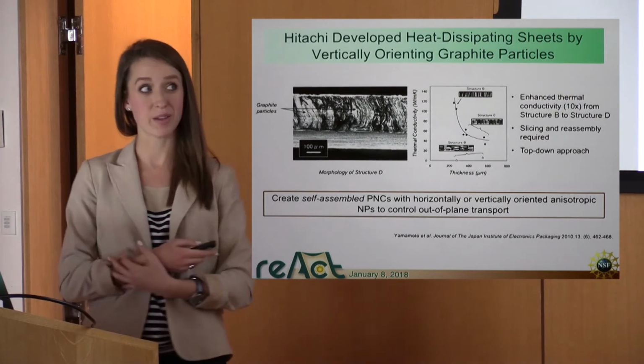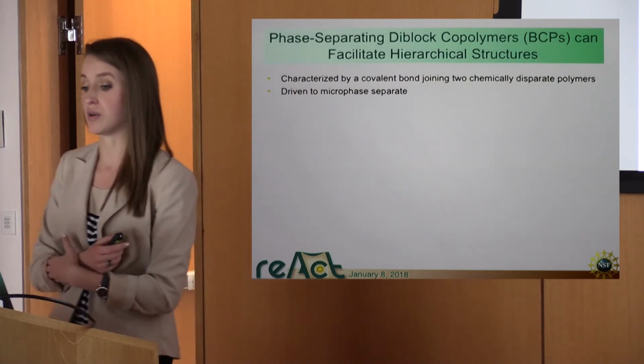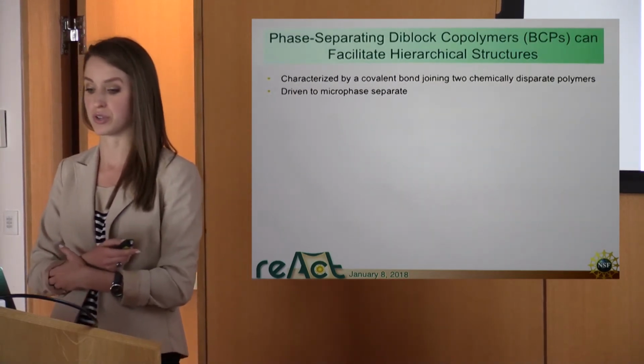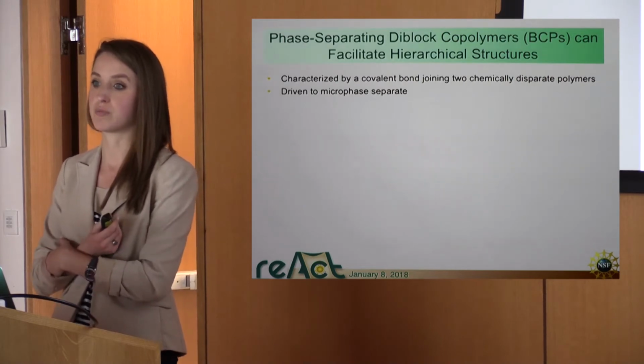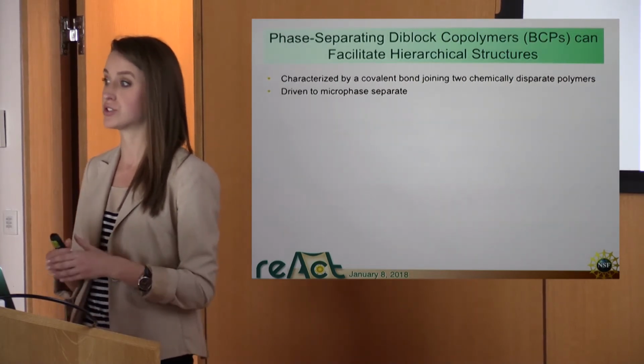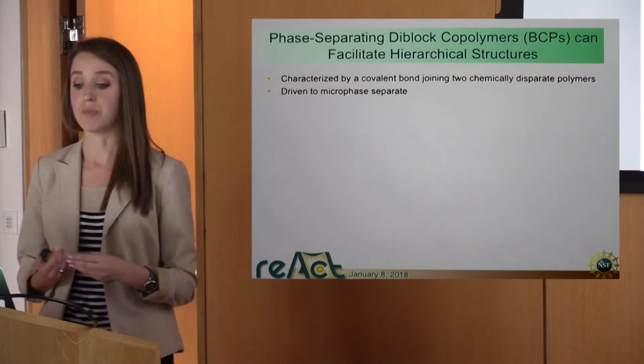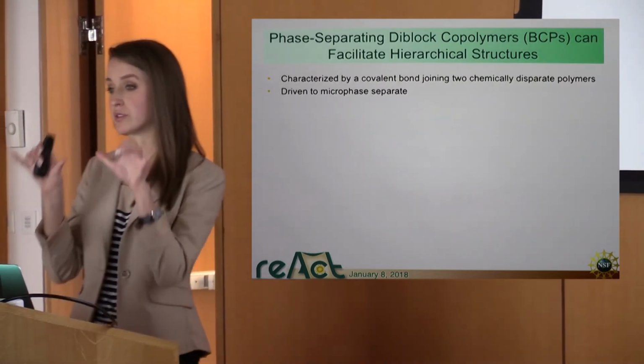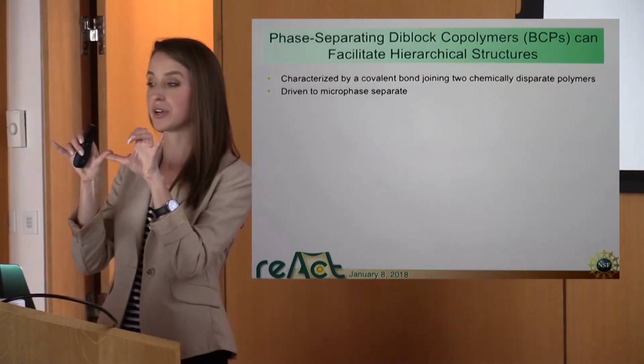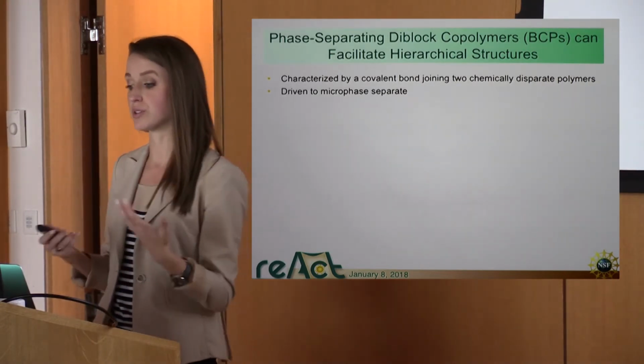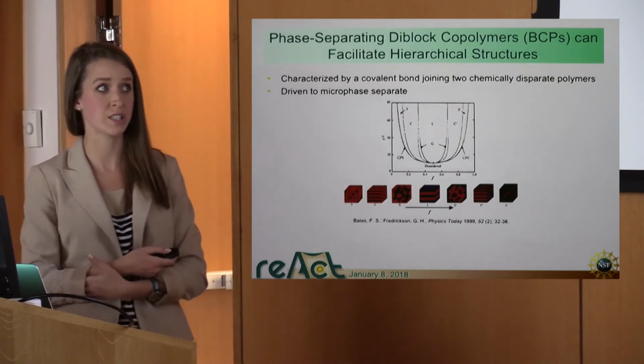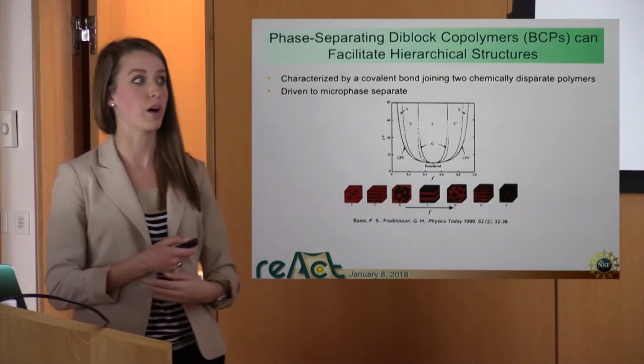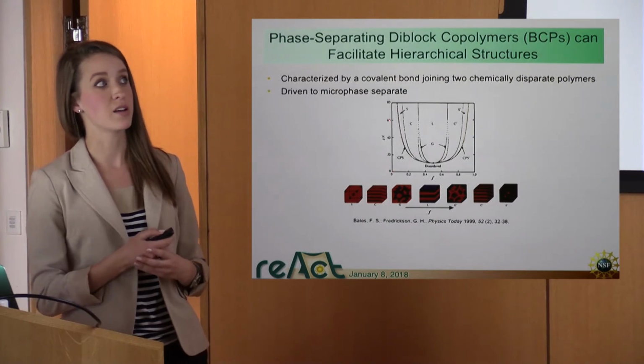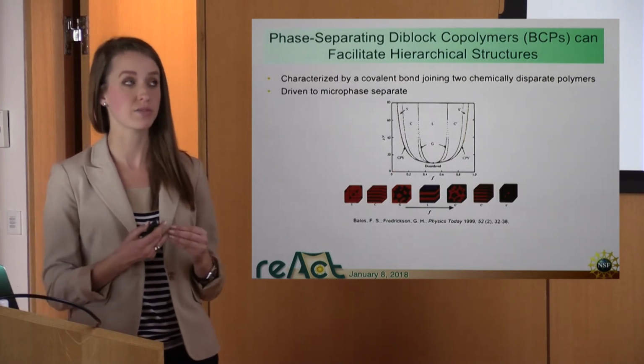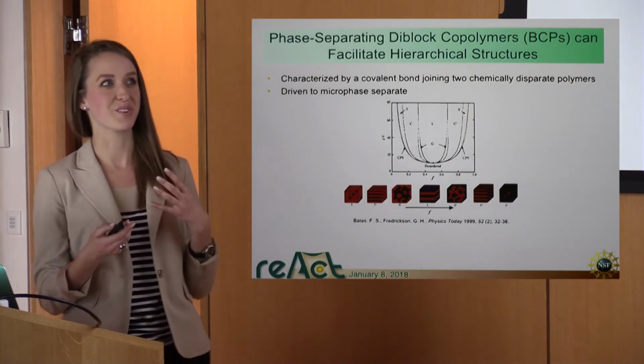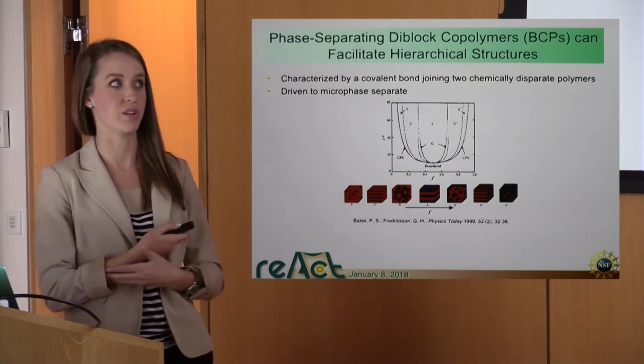So the way I am looking to do this is using block copolymers to facilitate a hierarchical structure. So block copolymers are characterized by covalently binding two dissimilar polymers that are driven to microphase separate, because now we have these two polymers that are attached together that don't want to be close to each other, but they can only go so far. So this is a typical phase diagram for a block copolymer, where here we're looking at the chi-N, which is the relative attraction between the two blocks.